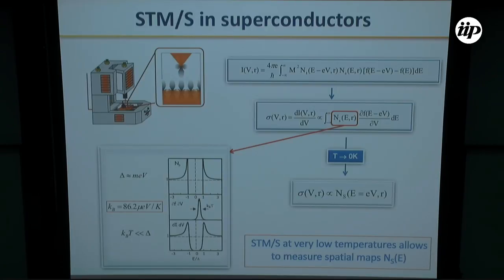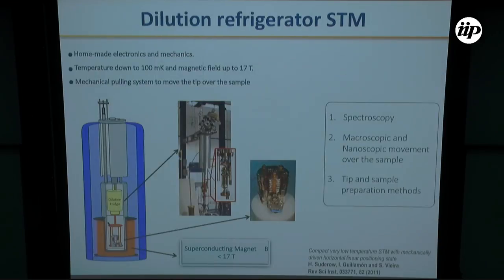Well, we have studied this material using scanning tunneling microscopy, and before I show you the data, I'm going to briefly introduce the experimental technique and also the facilities that we have in Madrid. As we also saw yesterday, scanning tunneling microscopy, when operated at very low temperatures, allows us to measure directly the local superconducting density of states. So it also allows us to measure the spatial variation of the density of states, and this gives the possibility to directly image the vortex lattice.